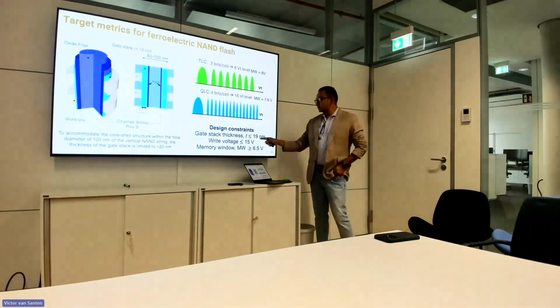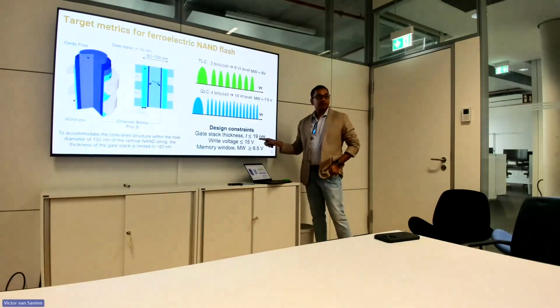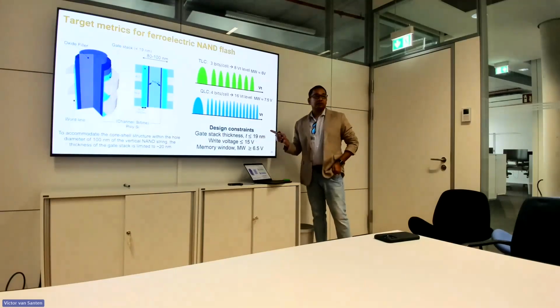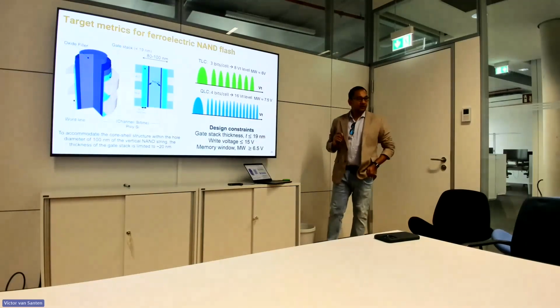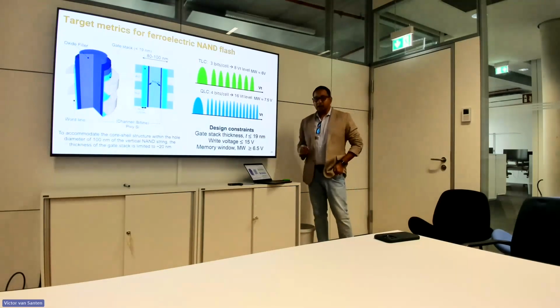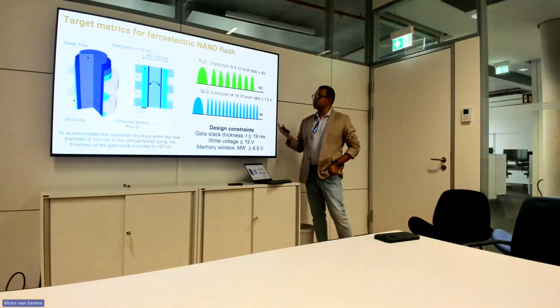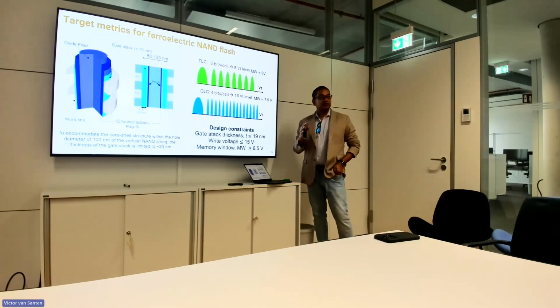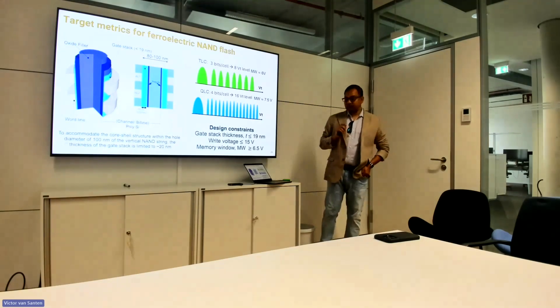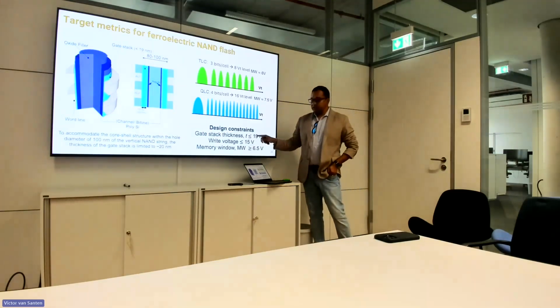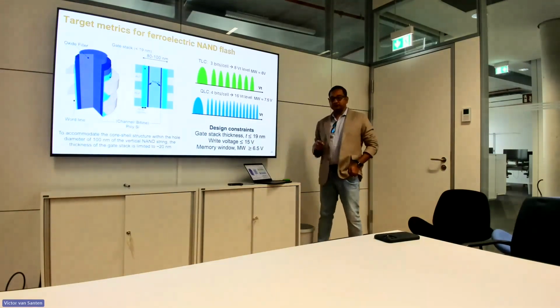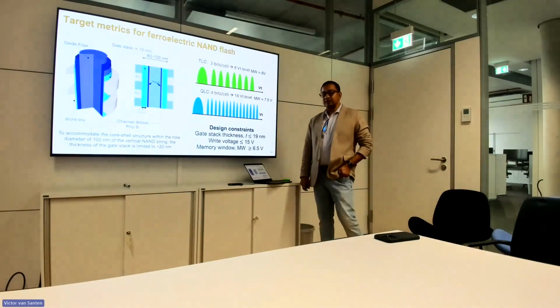And finally, as I said, today's NAND flash works at 20 volts. We want 15 volts to be the right voltage for NAND flash. Why 15 volts? I mean, even if we can get to 18 volts, it's great. But the thing is that once we want to introduce a new material system into the entire stack, it better be so much better than what we have already. So 15 volts was our initial target. And you need the positive, negative. Then positive 15 and negative 15.